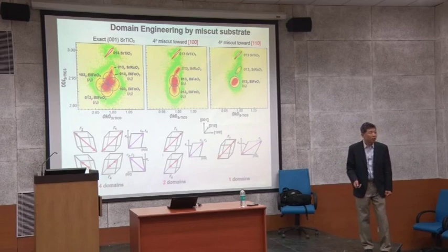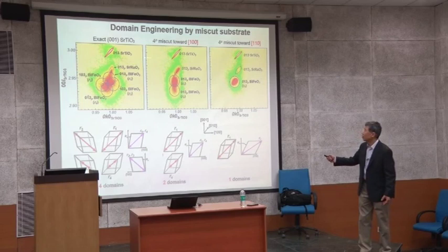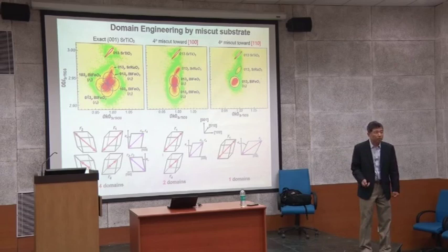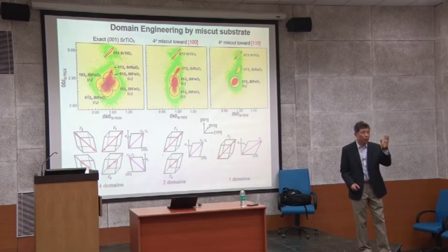So if we just look at X-ray diffraction without RSM, you scan it along that direction. Along that direction, maybe you miss this peak. Okay, you only draw the line here, and you just look at the shoulder. You look at this measurement, time slant, and you see only broad peaks like here. So in order to look at this domain structure, you have to look at mapping.